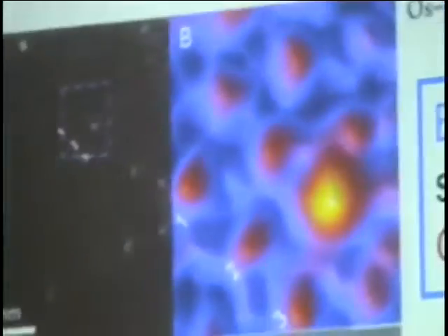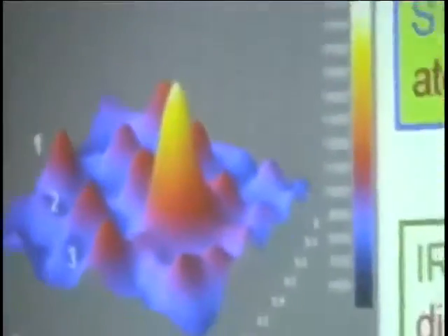So if you're looking onto this face of MgO, if you take a top view, you're looking down on columns of Mg and columns of O. And so it maximizes the contrast, and it turns out that the osmium atoms are directly above columns of magnesium atoms. So that gives us a basis for determining a structural model.